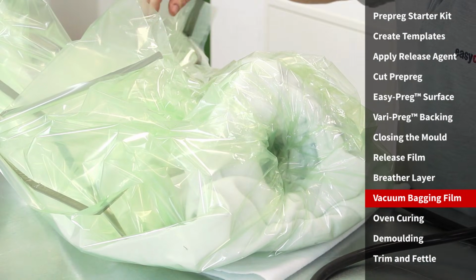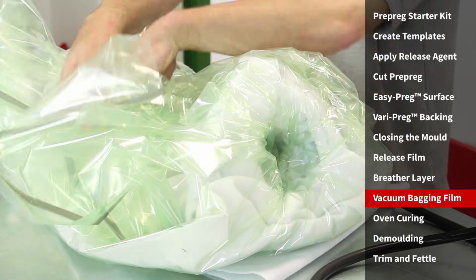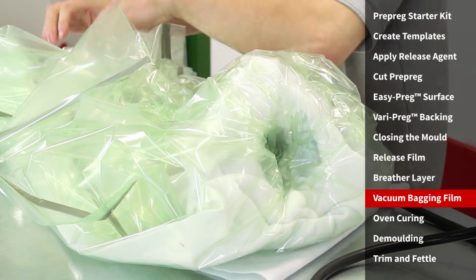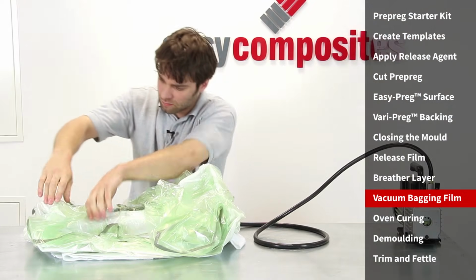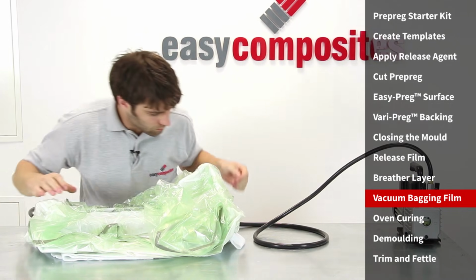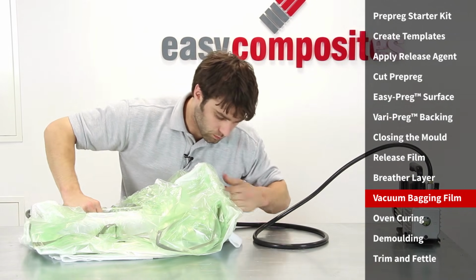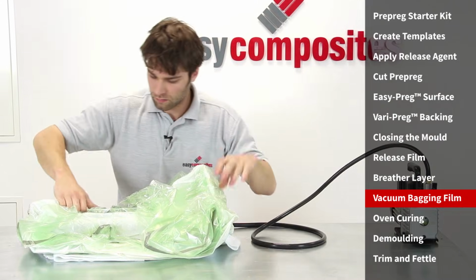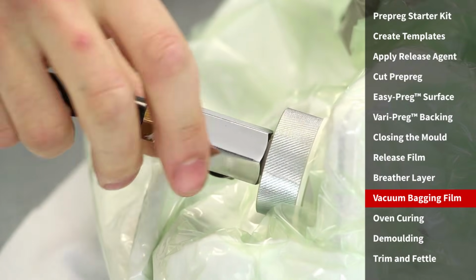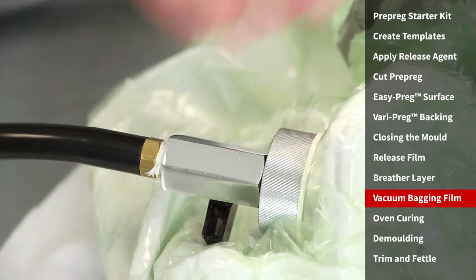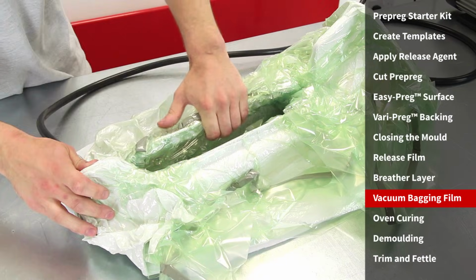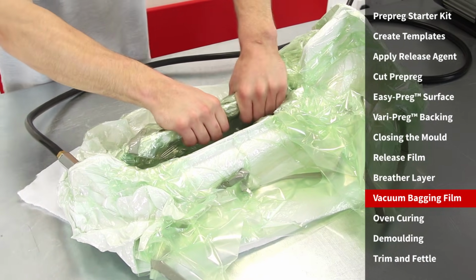As the bulk of the air is removed from the bag, you'll want to periodically close the vacuum valve to provide sufficient time to reposition the bag. It's essential that by the time the bag starts to tighten up, it's being carefully positioned and jostled into place so that it's properly into all of the corners of the mould without any bridging or tight areas.